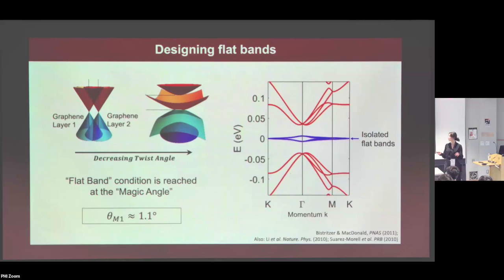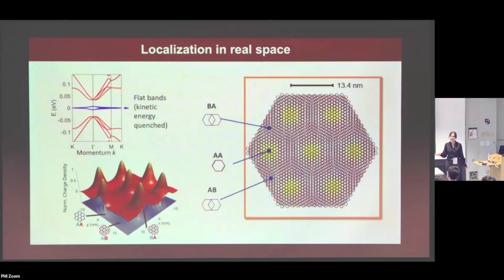Okay, so you already heard this 1,000 times in the last 3 days. When you twist 2 layers of graphene, you can form these sets of flat bands near zero energy. When you reach the twist angle of around 1.1 degrees, that's called the magic angle. And when you have this flat band condition, it means that your kinetic energy, your Fermi velocity of the electrons, will be almost quenched, and the electrons are going to be reluctant to move in space, and they're going to be stuck at these AA spots. Okay, so that's going to lead to strong interactions between them compared to the kinetic energy that they have in the system.